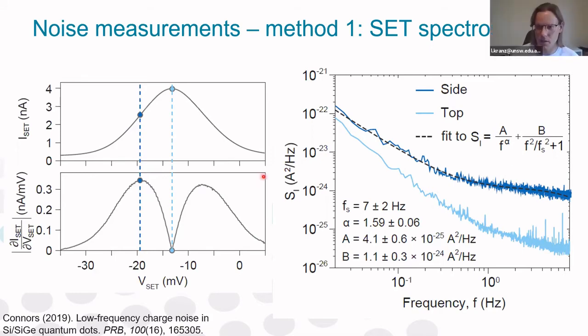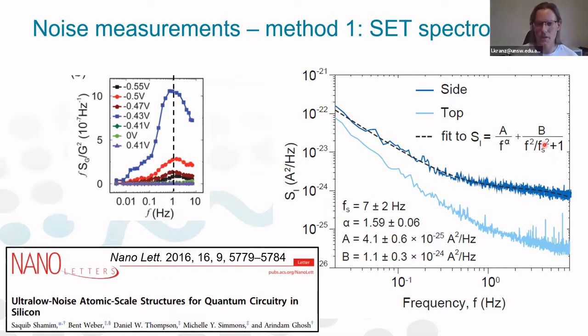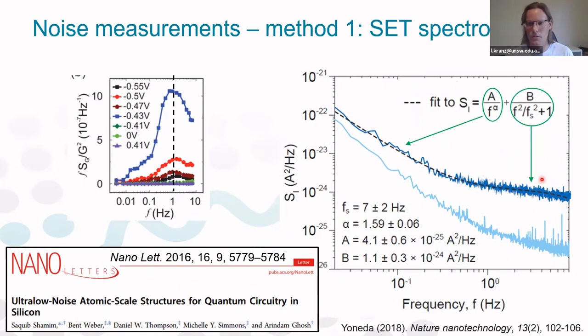So the fact that we observe a Lorentzian contribution to our spectrum is perhaps not surprising, because this was observed before in this paper that I'm showing here. What they observed is also this Lorentzian contribution at around 1 Hertz. And what the authors of this paper did is they calculated that the switching frequency of around 1 Hertz corresponds to the statistical distribution of charge traps at the silicon-silicon oxide interface. So for our case, the Lorentzian shoulder is around 7 Hertz. So it's the same order of magnitude, and we believe that this Lorentzian can potentially come from the defects at the surface. So in general, we have the power law contribution to our spectrum and the Lorentzian contribution, with the power law being in the lower frequencies.